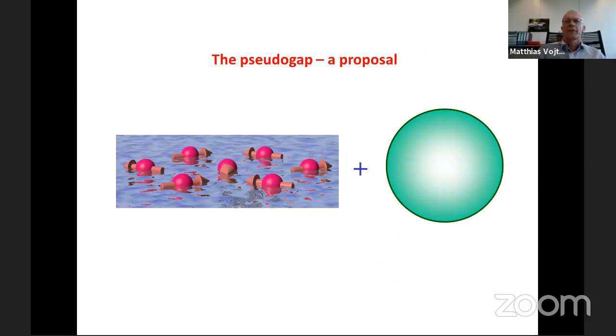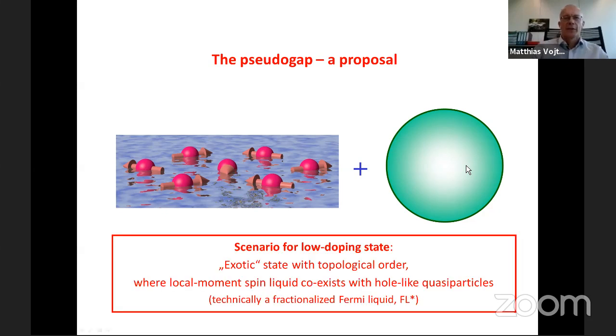The pseudogap is, and that is a story which has been shaped over the last 10 years or so, likely to be understood as the coexistence regime of a spin liquid and charge carriers which have a Fermi surface. So it will be an exotic state which has some type of topological order, where a spin liquid exists with hole-like quasi-particles. In other words, you start from a Mott insulator which has local moments. These local moments persist as a spin liquid, and the doped holes form carriers which essentially live an independent life. This is technically a fractionalized Fermi liquid, which I just described to you.